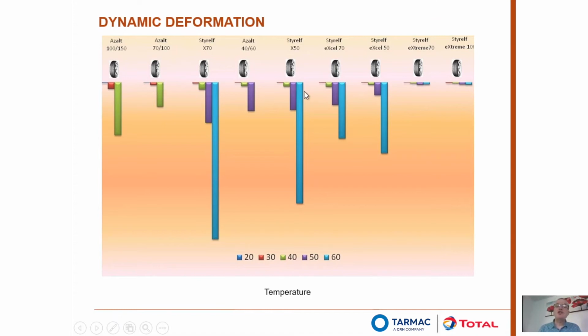If you then move towards something like an XL70 mid-range polymer, what you can see is that even at temperatures of 50 degrees C, we're still getting a little bit of resistance, but it's starting to go. You can see between 40 and 50 degrees C, you're starting to see a difference. And at 60 degrees C, it's definitely going.